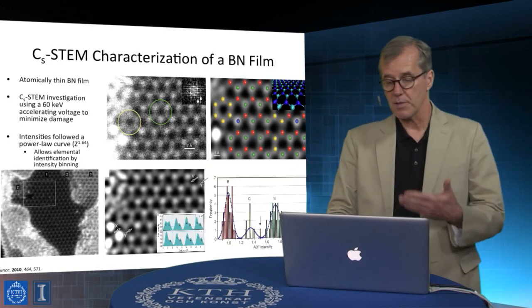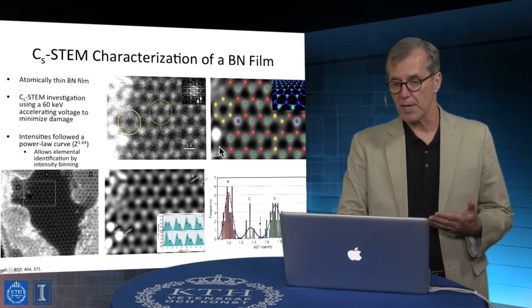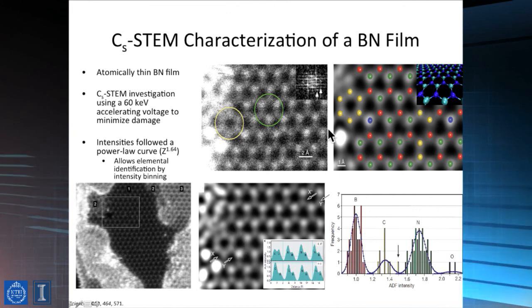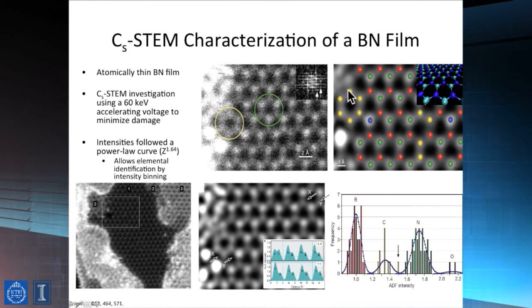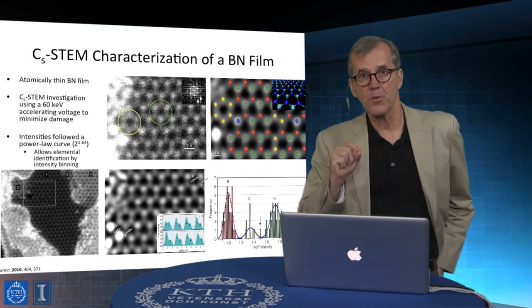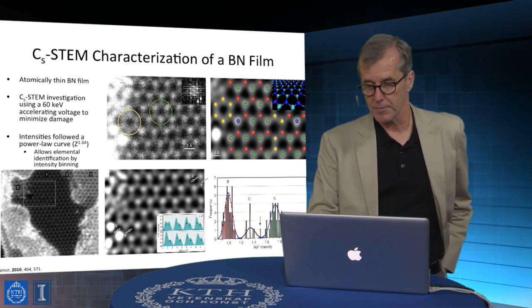And people have taken this to incredible depths. For example, it's a boron nitride thin film, but containing different amounts of carbon and oxygen impurities. You can look at an image, like there's the raw image, and find places where there's misplaced atoms of a different compositional form. Not everything is boron and nitrogen. Some of the things are actually oxygen and carbon. And this image of this monatomic plane of atoms shows that speciation difference just based on differences in the atomic number of the atoms involved.